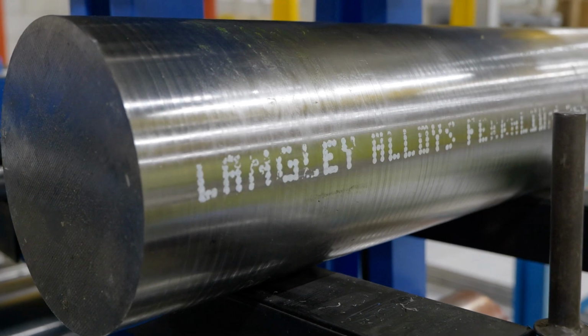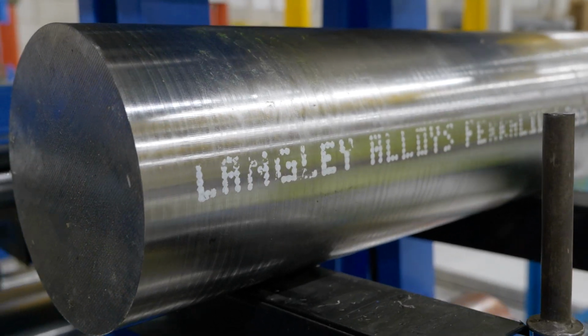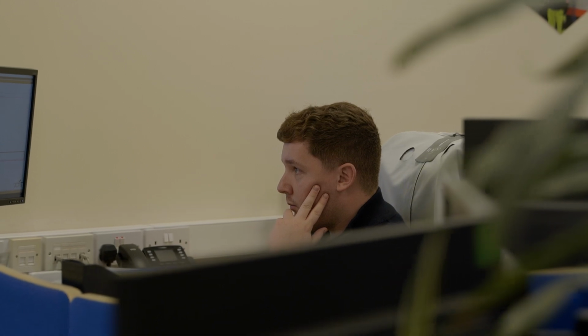The differences are small, relatively subtle. I'd still argue the case that Ferralium's the higher strength alloy, which will have its advantages for designers. In terms of what's actually in it, Ferralium's got a bit more copper, which is useful for acid resistance, but 32760 has a bit less copper, and they're using tungsten instead, which various papers and articles say will also help the corrosion resistance. So you pick an expert and you ask them their opinion, and it'll probably be slightly different depending on which business they're representing. It's a bit like my nan's red velvet cake versus your nan's red velvet cake.